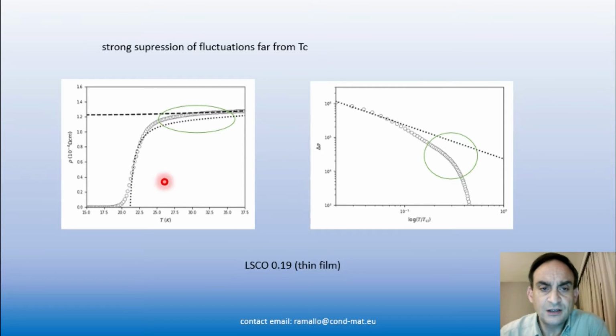There, what is seen is that the fluctuations actually go to zero much faster than predicted by the theory. The Aslamazov-Larkin theory will be the dotted line. Normal state background will be this dashed line, and you see that the data really go to the background much faster than predicted by the theory. If you express this in terms of the log-log slope and you extend it to lower temperature, you see that there is a very drastic drop of the fluctuations, faster than any power law, in fact.